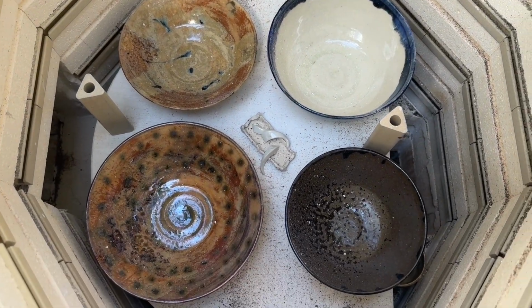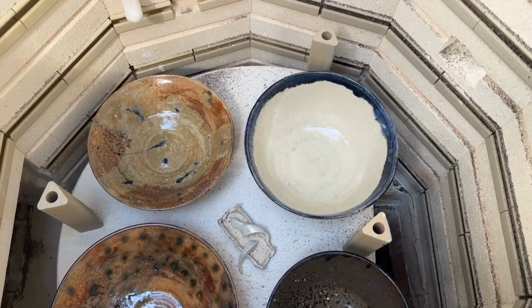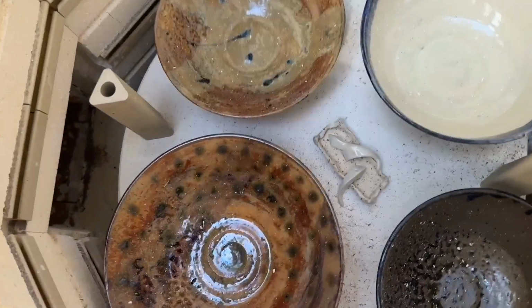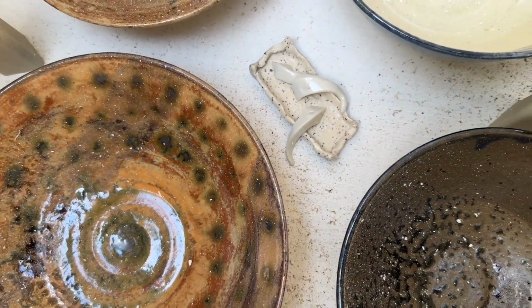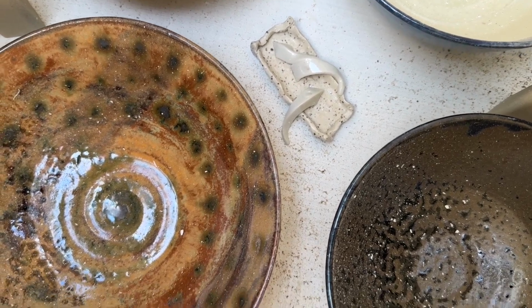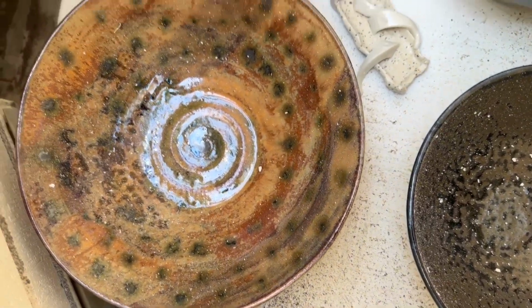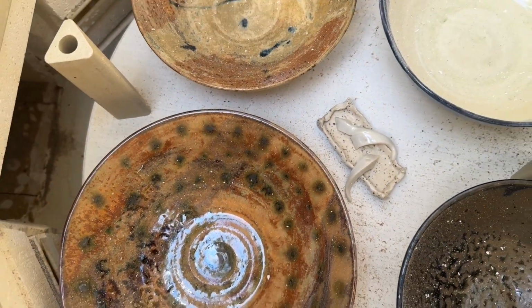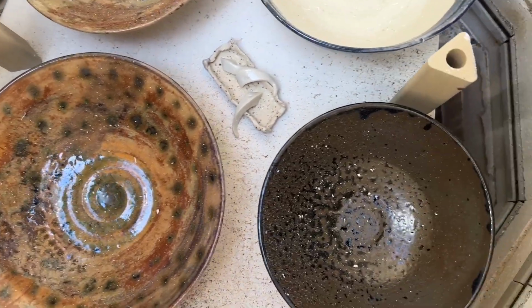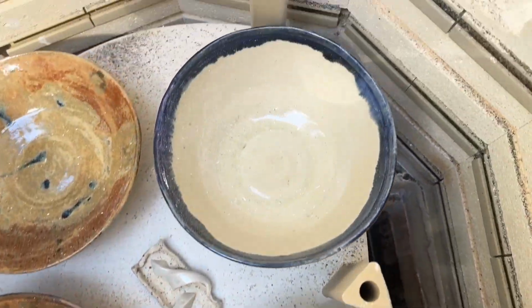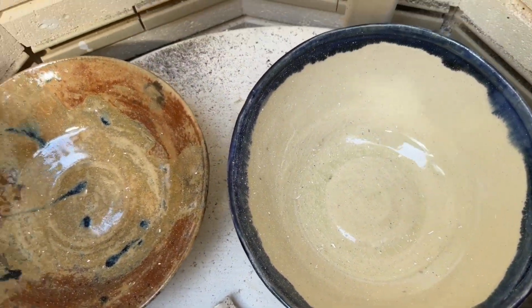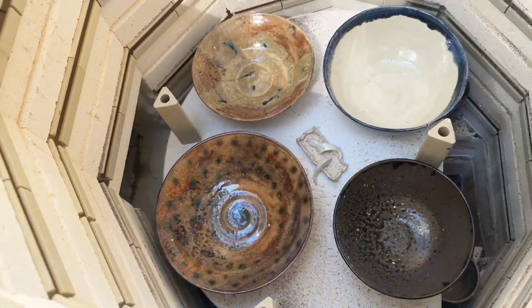So, unloading the kiln. Cone 7 here is lying flat, so this must have been cone 8 or 9 even. I'm not real sure. But the pots end up surviving and coming out pretty cool. The blue and white bowl had a little crazing, so that glaze isn't really agreeing with that clay body.